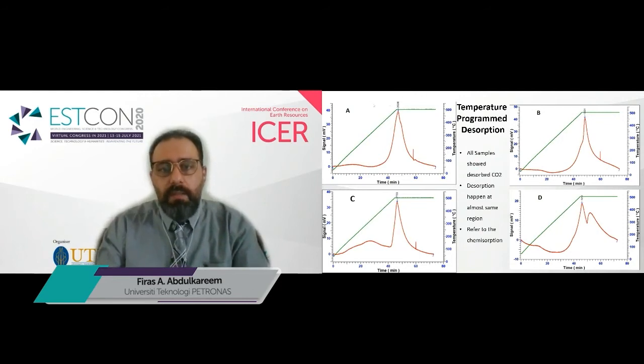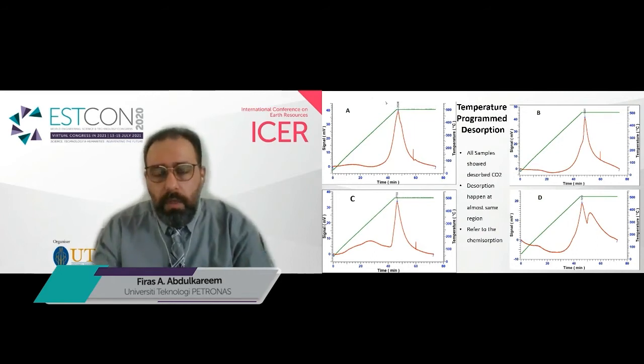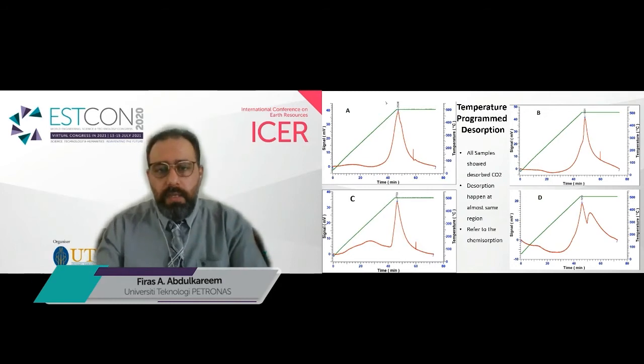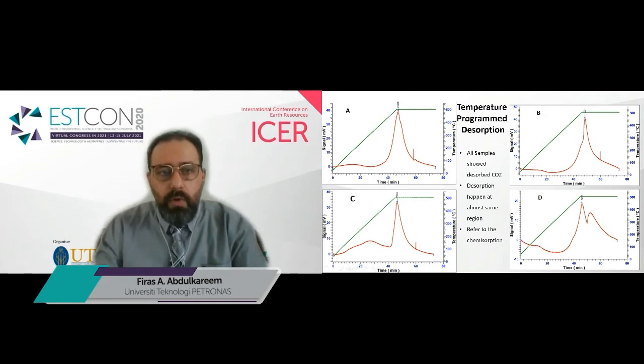So if we have any CO2 released after the heating process, it means that some CO2 has been chemisorbed, because it's released only by the heat and not by the purging of the nitrogen. For the 4 samples we have here, we can see that some CO2 is desorbed at more or less the same time, about 50 minutes, more or less 1 hour after heating, until we reach somehow 500 degrees C, which is considered a strong point for breaking down.